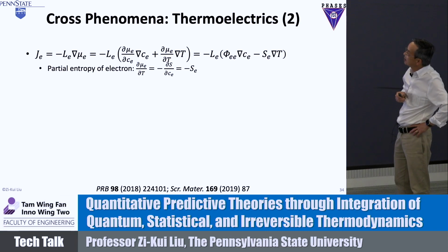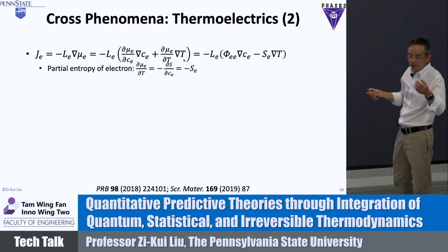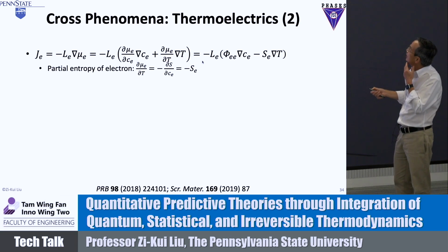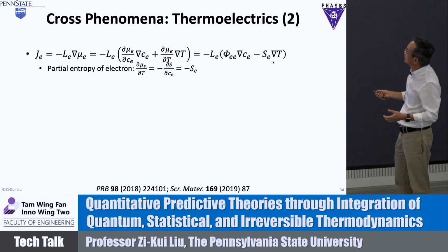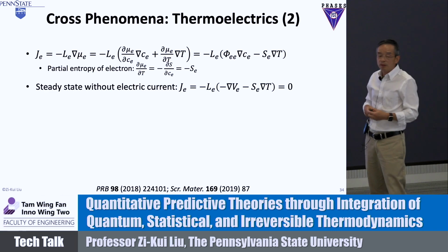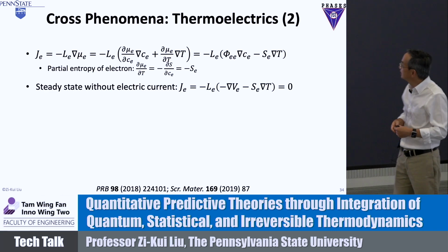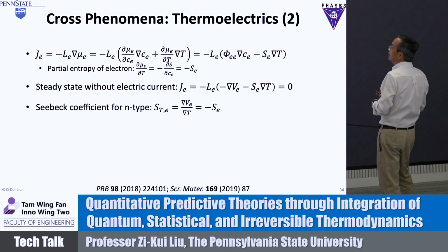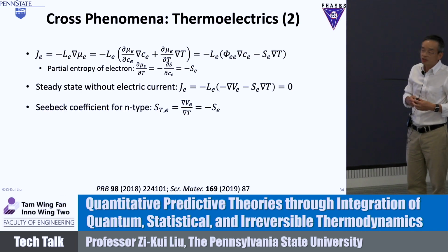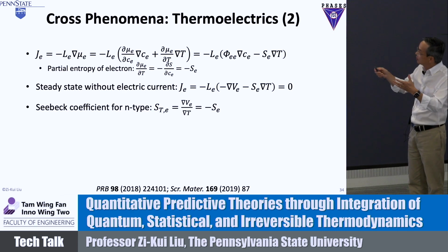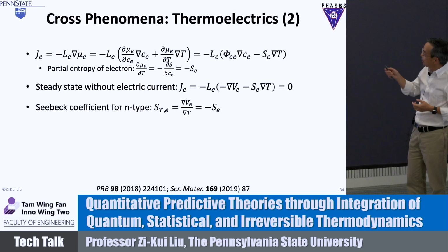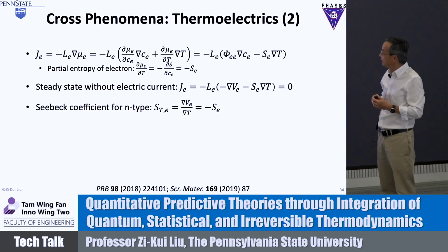If we write the flux equation for electrons like this, and the chemical potential is a function of electron concentration and temperature, that goes back to the Thomson equation, before Onsager's formula. Then you have two terms now. The electron gradient gives you the internal voltage, and there is a temperature gradient too. It turns out the Seebeck coefficient is basically the partial entropy of the electron. Now you can make the flux 0 with no current, and you get the Seebeck coefficient. It's the partial entropy of the electron, but because the electron goes in the opposite direction of the current, you get a minus sign. That's why the Seebeck coefficient for N-type is negative.